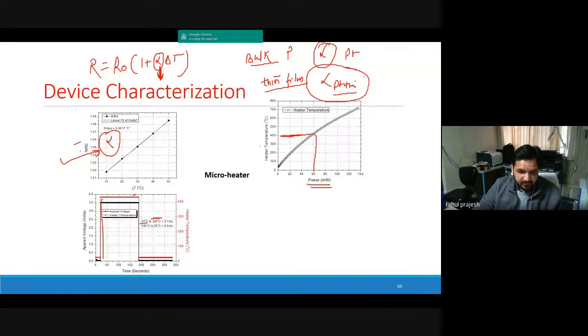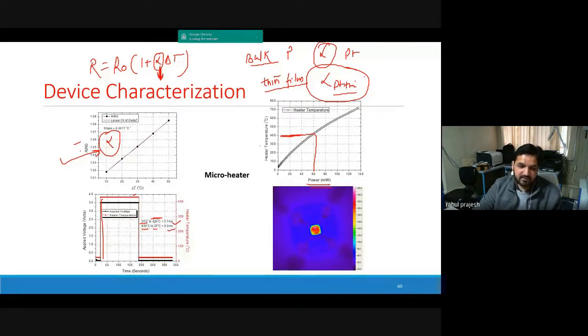So 25 to 430 takes 5.7 milliseconds, and then 430 to 25 takes 6 milliseconds. So this is a very fast response of the device. And then is the IR imaging. So this is the actual test of your device, of the micro heater basically.